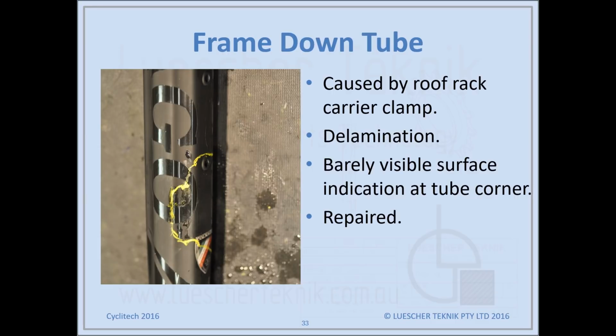There was almost no visible indication on the surface. Very fine little cracks on the corners, but the damage area was much more substantial than that. This one was repaired and put back into service with no issues.